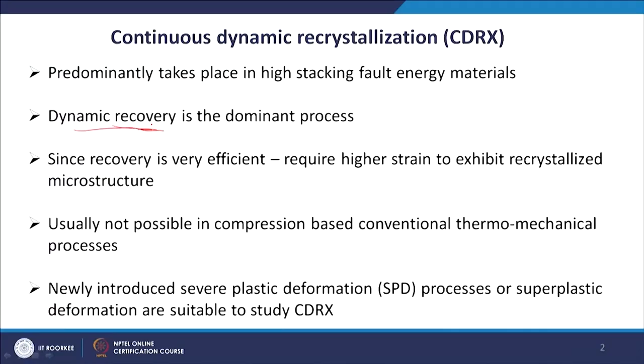Why does this kind of process take place especially in high stacking fault energy materials? Because recovery is very efficient. When recovery is very efficient, dislocations can easily recover. I cannot have a discontinuous dynamic recrystallization which requires a certain amount of dislocation density. So to have a recrystallization process, I need higher strain to exhibit a recrystallized microstructure in case of continuous dynamic recrystallization. At lower strain you will see a dynamically recovered microstructure, but at higher strains you will start seeing recrystallization.